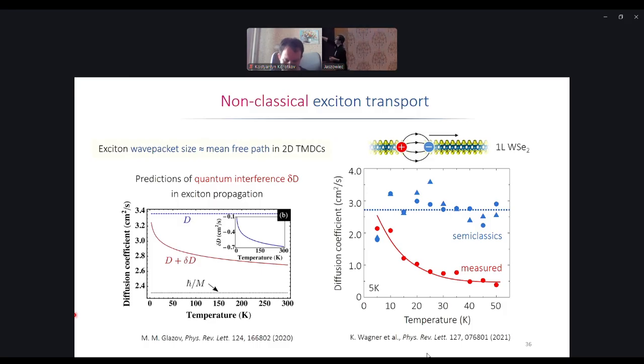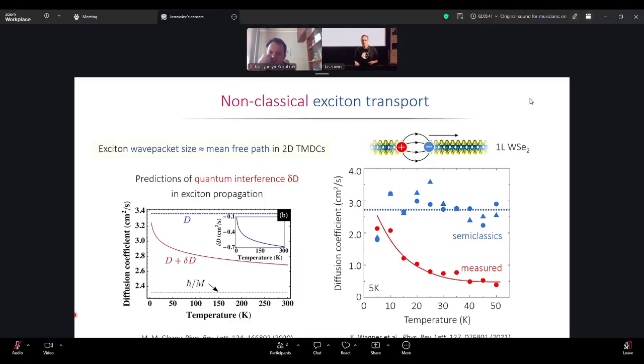It doesn't match in terms of numbers, so one should not call it weak localization, but what it shows is that also in the experiment, the actual transport can deviate from the semi-classical prediction, and also, as you can see, it is not hopping, not temperature activated, which means that taking the quantum mechanical nature of the exciton into account beyond the semi-classical approximation can be relevant for a number of systems under study, and it's not an easy theoretical problem to solve.